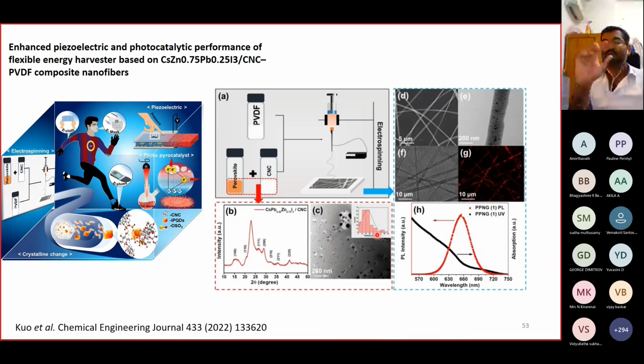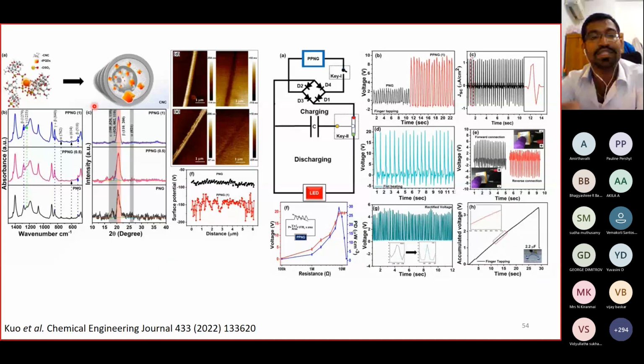And in this case, we use some piezoelectric polymer called PVDF, and then we use our perovskite material, quantum dots. And then here you can see the quantum dots. There are many quantum dots inside the nanofibers, and they have some colors also because this kind of iodide-based perovskites, they are exhibiting the red color. So we can easily notice the presence of perovskite quantum dots inside the fiber with the help of EDS or confocal microscopy. And this is the schematic. You can visualize how the nanofibers will be and how the quantum dots are inside, encapsulated very well inside, so that perovskite can be stable over a period of time.